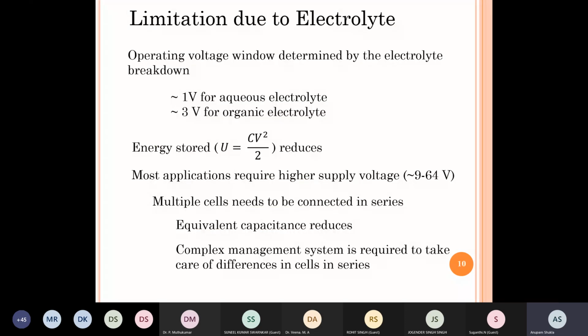Now, what are the limitations that come because of the electrolyte? The operating voltage window is basically determined by the electrolyte breakdown. As we discussed in the previous slide, it is about 1 volt if one is using aqueous electrolyte. It becomes around 3 volts if organic electrolytes are used, but this is still much smaller than where dielectric capacitors can go. A dielectric capacitor can go up to tens of volts, up to the voltage where the dielectric in between does not break down. An electrolytic capacitor can go up to hundreds of volts because they have an alumina layer, aluminum oxide.